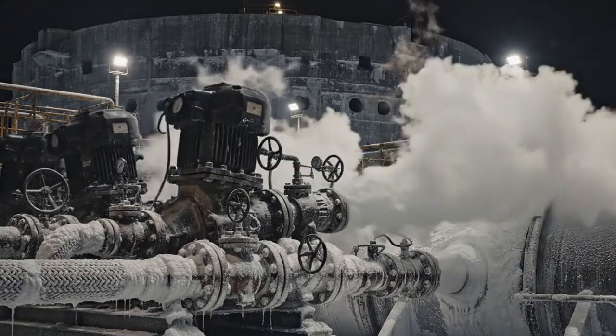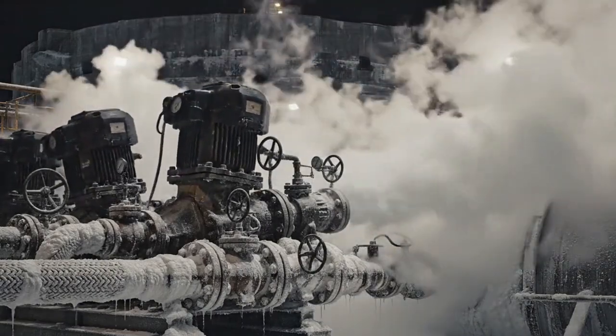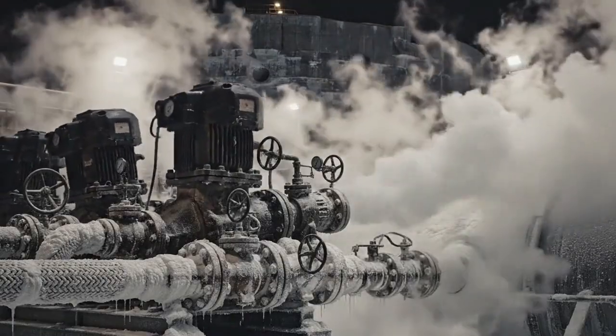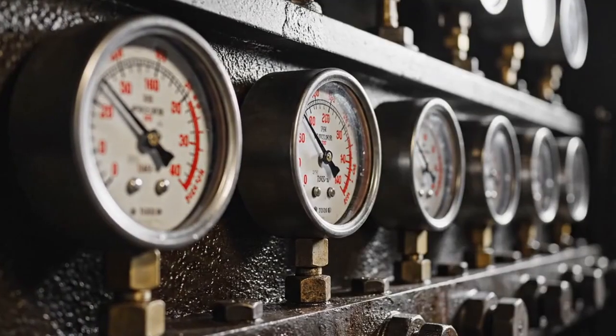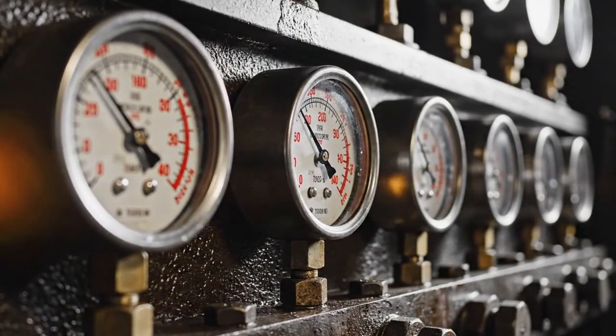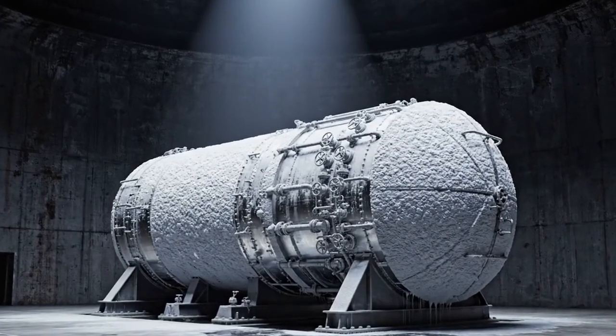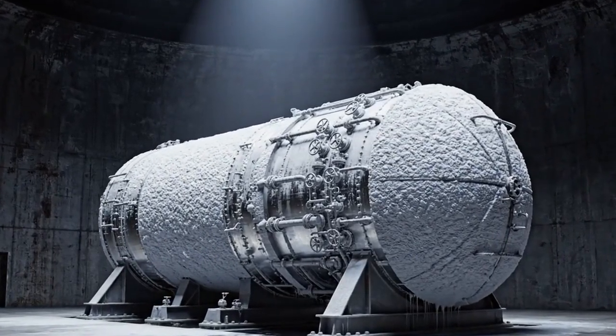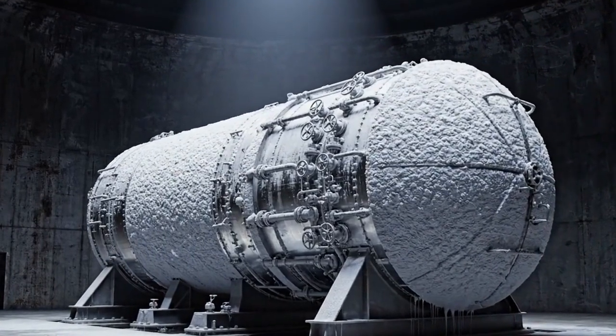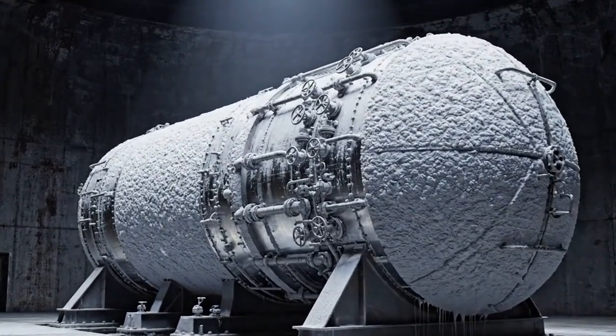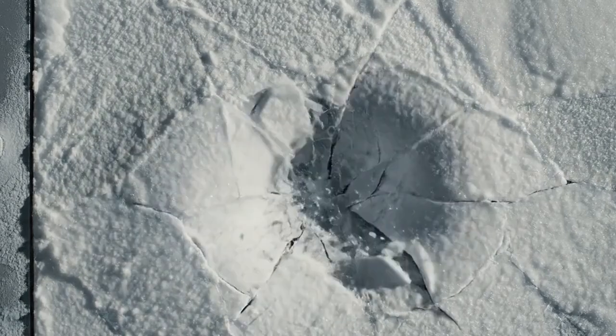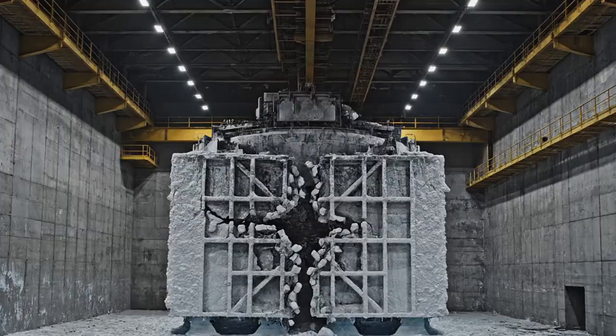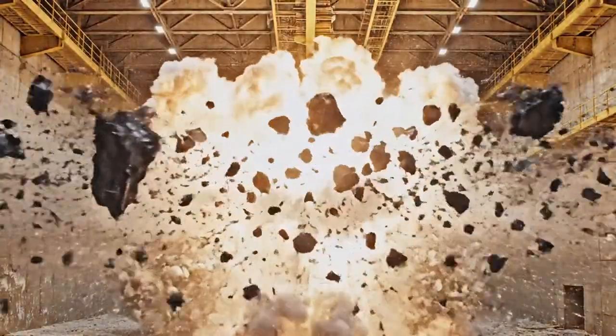Once thermal equilibrium is reached, high-capacity pumps force additional cryogenic fluid into the sealed tank, steadily increasing the internal hydrostatic pressure. The structure is first pressurized to its maximum expected operating pressure, followed by a proof pressure holding phase to verify seal integrity. However, for a qualification article, the pressurization continues relentlessly until the physical yield strength of the material is violently exceeded. The tank intentionally ruptures.